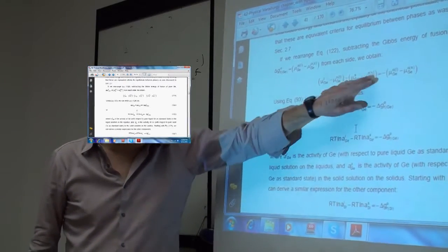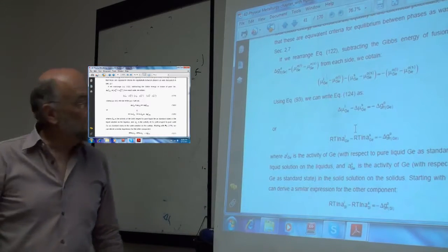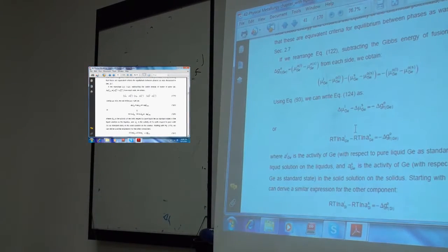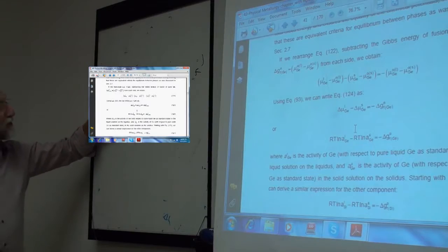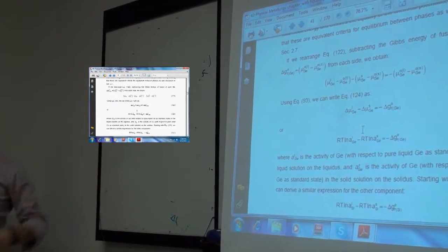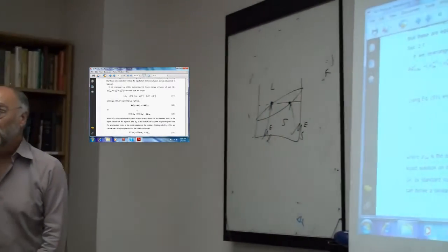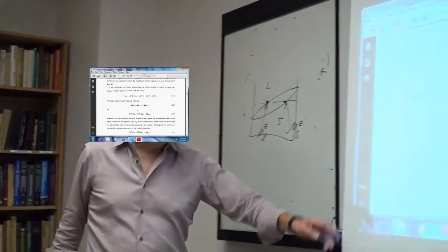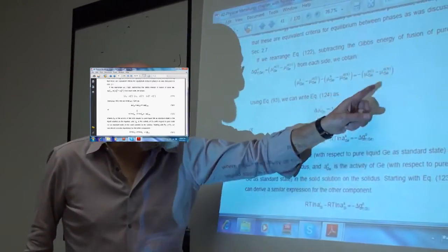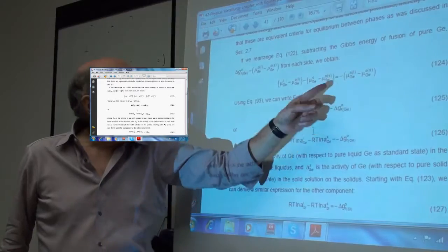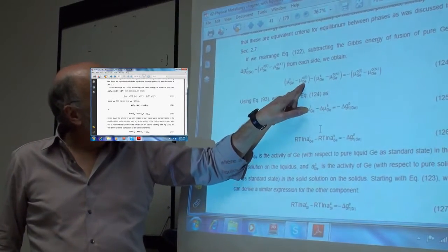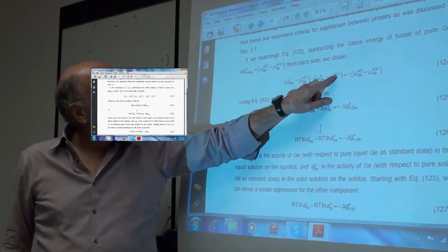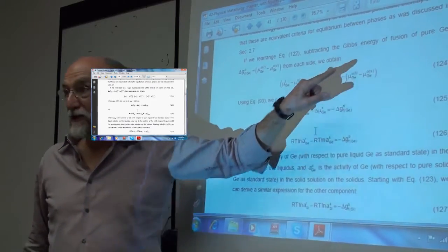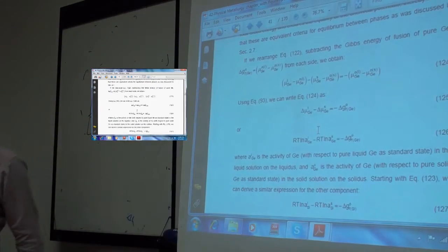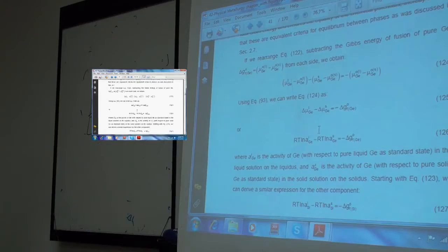The solid standard states aren't the same. If two phases are in equilibrium, a component will have the same activity in both phases, provided it's with respect to the same standard state. If it's not with respect to the same standard state, then you have to have a standard state change, which is what this is. This is simply the difference. Here the standard state is mu naught liquid, this is mu naught solid, this is the difference in the standard states. Okay, so be careful when you say activities are equal to 1.